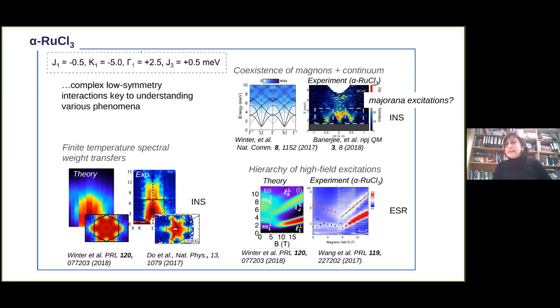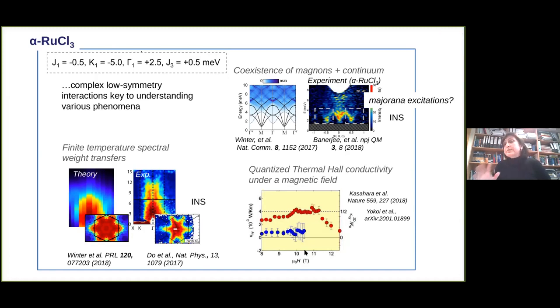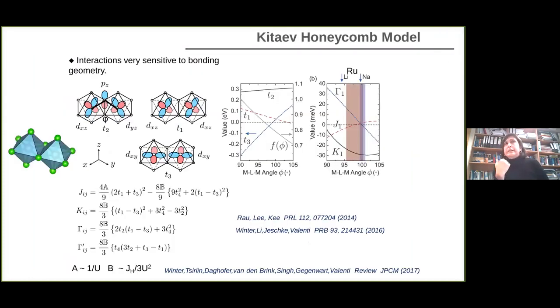And here, in fact, in the last years, there is a measurement that has been the center of discussion for this material, which is the observation by the group of Yuji Matsuda in Tokyo of quantized thermal Hall conductivity on the magnetic field. But what I want to do today, because I'm going to build structures for this system, is mostly concentrate myself on aspects like strain effects, because I'm going to make a heterostructure between two systems where there is a strong lattice mismatch. That means that there is going to be some effects of strain in ruthenium trichloride as well as in graphene, although we expect that the effects in ruthenium trichloride are much stronger.